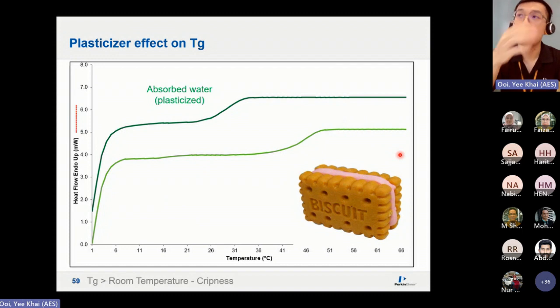Glass transition temperature is derived from glass material. Glass doesn't melt because glass is fully amorphous. It just goes from the glassy state into the rubbery state. You have seen people blow glass before. At high temperature, it starts to become rubbery, becomes soft so that you can mold it into a certain shape. This is why the term TG is called glass transition temperature.